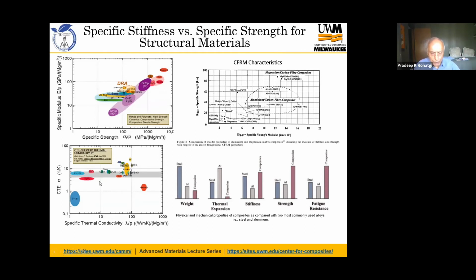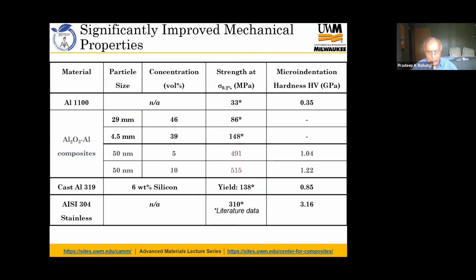Now, why do we use metal composites in thermal management systems? This is a plot of coefficient of thermal expansion versus thermal conductivity, lambda by rho. And in our thermal management systems, in our computers, we want the CTE to be of a given value so that CTE is the same as the chip. The only thing is you want the thermal conductivity by density to be as high as possible. And this is what you see here. Older materials like Kovar or Invar are here, but when you make metal composites, you have much higher lambda by rho value. And this is why in all the computers, you use metal matrix composites as heat sinks.